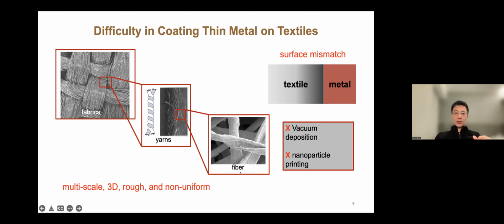So in terms of structure, the fiber is 3-dimensional. And fabrics and yarns are also 3-dimensional. They are very rough, the surface is not uniform, and sometimes they're a little bit dirty, right? Because they trap lots of particles. So it will be very difficult to use clean-room type technology, for example vacuum deposition, or even nanoparticle printing, to make this metal deposition on the textile surface.